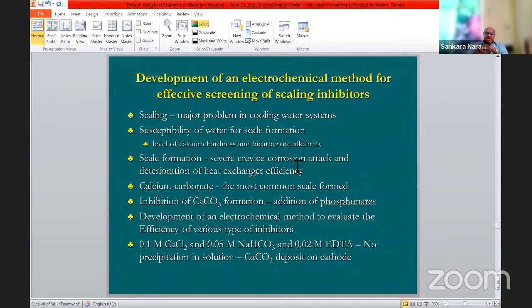What we did is we took calcium chloride and sodium bicarbonate, because calcium and bicarbonate are the important factors. We took 0.1 molar calcium chloride and mixed it with 0.05 molar sodium bicarbonate. To avoid initial rapid precipitation, because mixing them would immediately form calcium carbonate precipitate, we added 0.02 molar EDTA as a complexing agent. That complexes the calcium, so the calcium ions are not freely available for formation of calcium carbonate. Since we added the complexing agent, there is no precipitation and the solution remains clear. But this solution can be used to deposit calcium carbonate on the cathode.